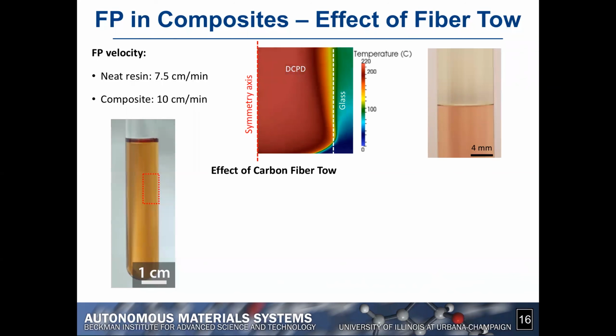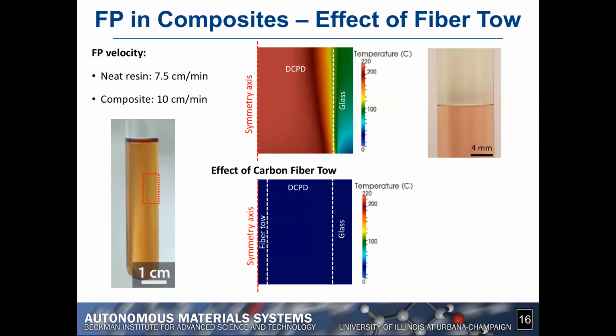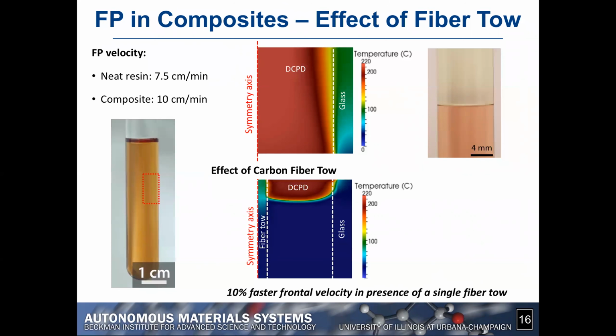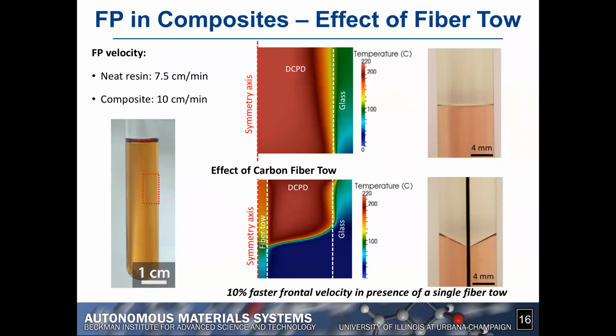Now, if we start to introduce a carbon fiber tow, we know that carbon fibers are much more conductive than DCPD. So we expect that heat conduction through the carbon fibers will affect the speed and the shape of the front. And indeed, if we do a simulation where we introduce a carbon fiber tow in the middle of the specimen, we can see that very quickly the increased thermal conductivity in the fiber tow affects the shape of the front, as observed once again experimentally on the bottom right figure. And we observe that the front goes faster in this kind of model system.